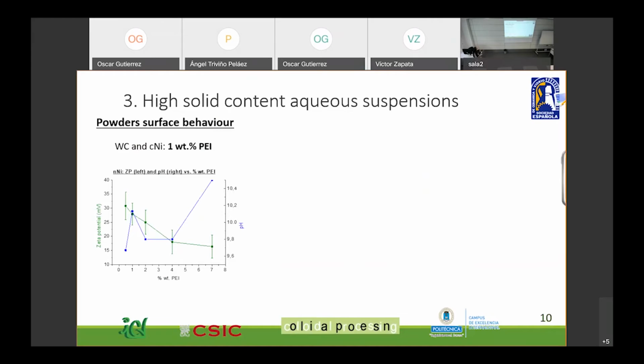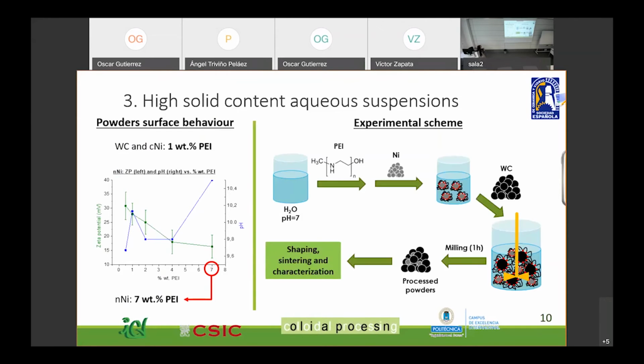In the case of these two powders, the tungsten carbide powder and the commercial nickel powder, we again determined there's 1% of this PEI polyelectrolyte to add to our suspensions. But in the case of nanometric nickel, the optimal amount is determined here, where the zeta potential value stabilizes, and it will be 7% of PEI in weight.